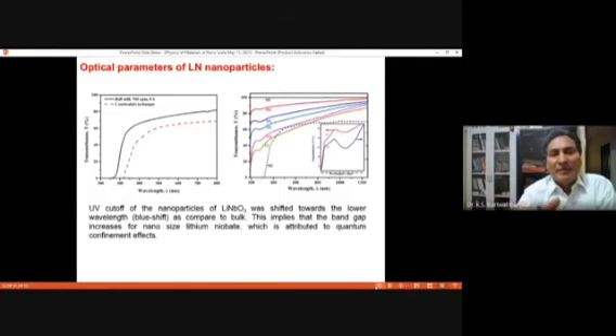And optical parameters, you can see where it falls. Basically, this blue shift tells how the band gap is shifting, so where it can be useful. For a particular application, particularly when you are using that material for optical devices, you need this information on whether it will be useful or not. Otherwise, you have to change the size. So if you have a 30 nanometer size, it may not give in this range, so you have to change the size to 20 nanometer or 60 nanometer or something. Sometimes it is 100 nanometer, very near to the boundary, so it can be useful for that particular application.